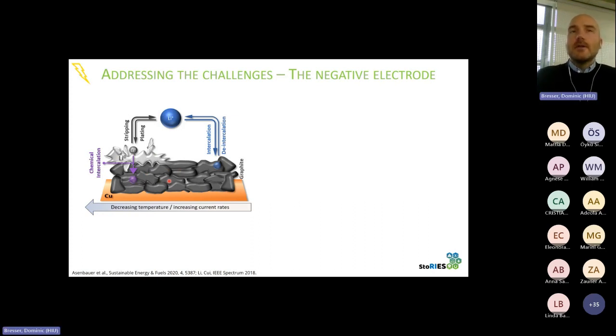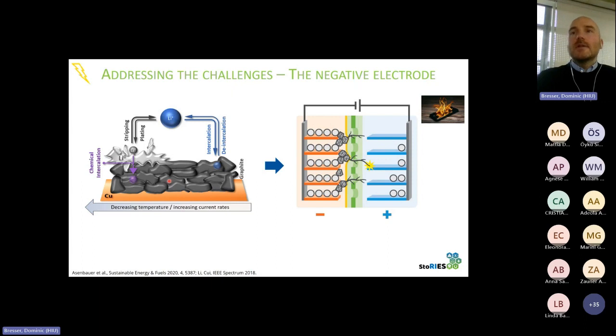And that has an impact on what I mentioned earlier, the SEI, the solid electrolyte interface, because in such a case we continuously decompose electrolyte at the interface between the negative electrode and the electrolyte, which is an issue for faster aging. But it also poses the risk that this metallic lithium deposits in so-called dendritic structures. And these dendrites then grow through the separator that is physically separating the anode and cathode, and then it might result in a short circuit, as schematized here. And this short circuit might result in a thermal runaway, and then eventually, in the worst case, a fire of the battery cell. This is not a real fire, as you can see, it's a kind of animation, but that's the risk that we're facing.